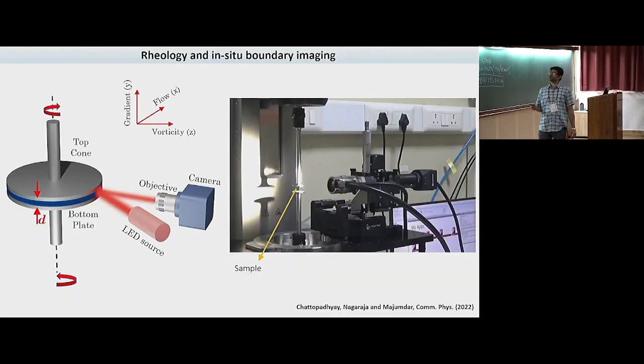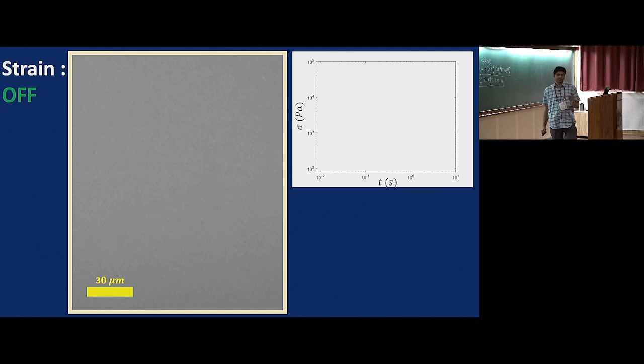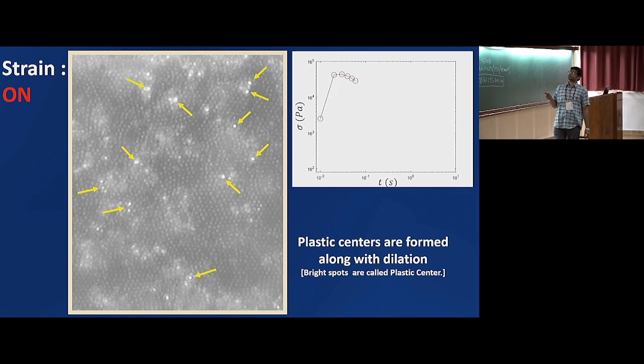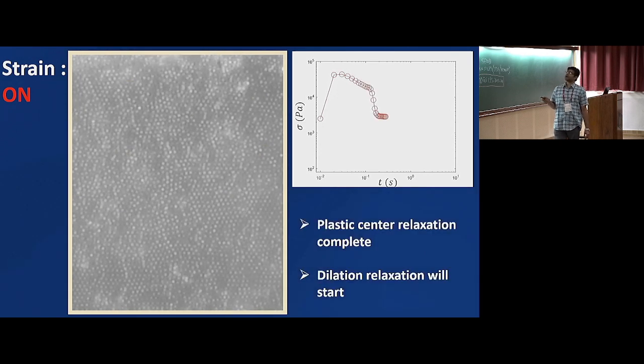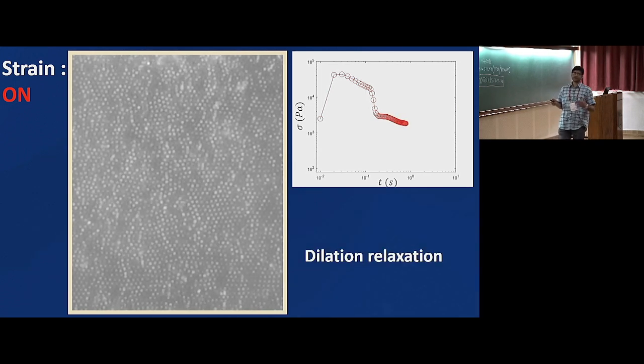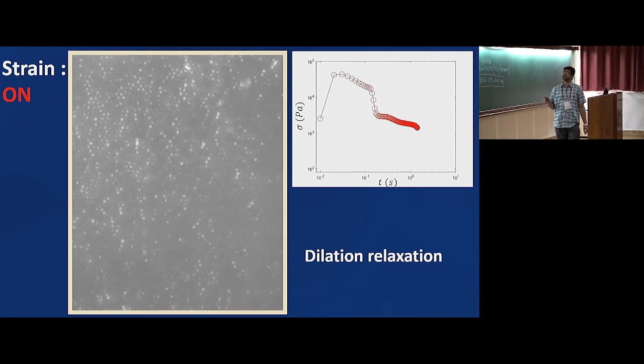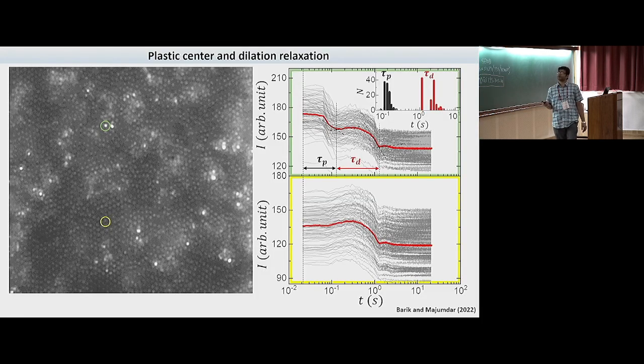Let me go back once more. What you'll see is that there are very bright spots in the system, and in the background there are these protruding particles which are not so bright. Those bright spots are linked to plasticity. During the stress relaxation, in the first part, those plastic spots relax first, and then slowly these other particles relax, and eventually, as the system goes back to the liquid-like state, the relaxation becomes complete. Now what we did was plot the intensity as a function of time for these very bright spots, which are plastic centers.